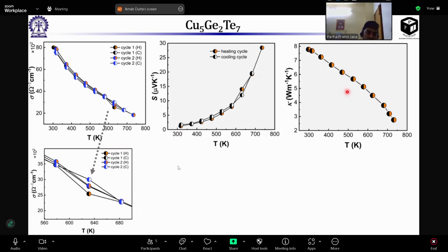Solving the structure would be good, but if you get some more insight from the band structure and also the phonons. Since the structure is solved, one thing we can do for sure is we have an automated code to study the intrinsic thermal conductivity of the material, so we will run that code. What it basically does is DFPT, density functional perturbation theory. It does an elastic relaxation of the unit cell, so it's only in the elastic limit. There will be some anharmonicity, but in the small displacement limit, and you can look at four-phonon interactions. It's called AutoKappa. We have the code for it already, and it runs on a supercomputer. It's already automated, and the analysis is relatively straightforward, so we can actually do that.